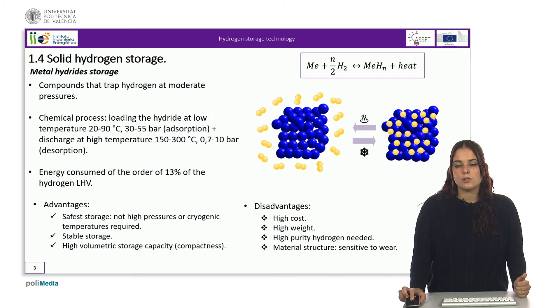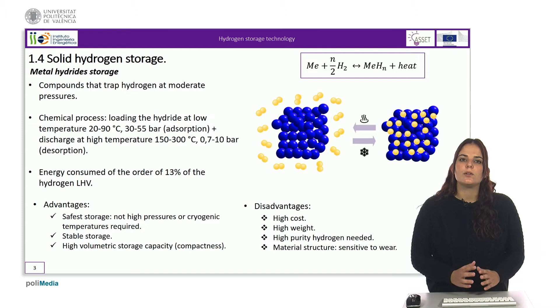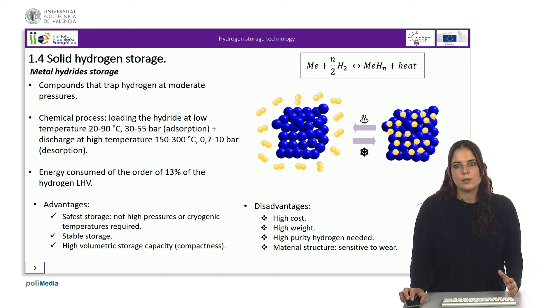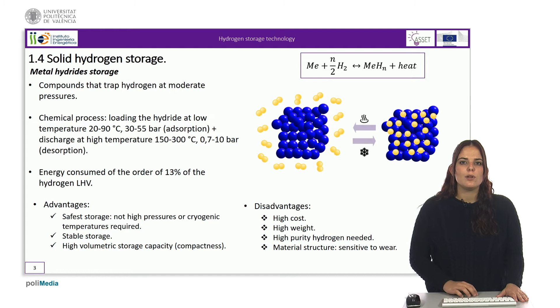However, there are also some disadvantages such as its high cost, its weight, and the need for high purity hydrogen. Metal hydrides must be charged with high purity hydrogen or they will be contaminated with a corresponding loss of capacity, which can be reactivated to a certain extent with heat. Another problem associated with metal hydrides concerns their structure. Metal hydrides are usually produced in the form of grains or dust to increase the surface area available for gas storage, and this particulate material is very sensitive to wear which reduces its performance.